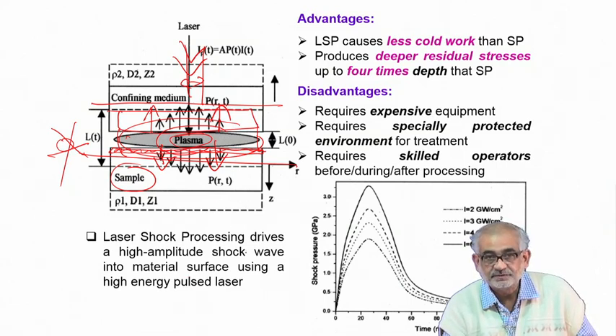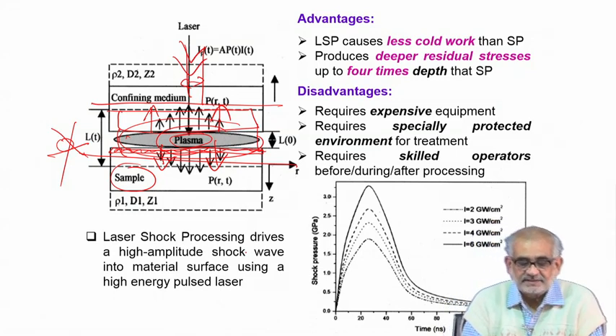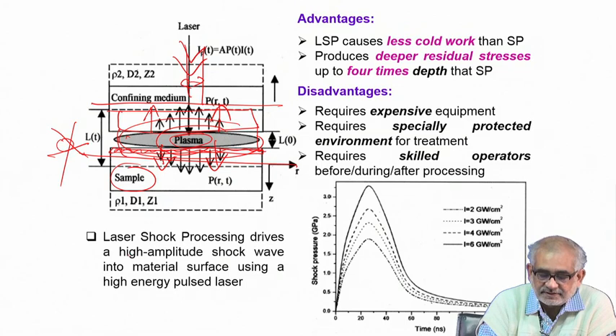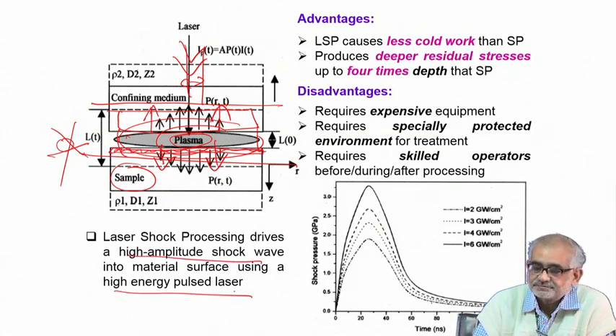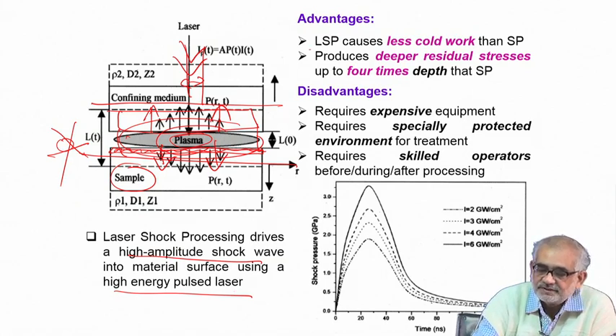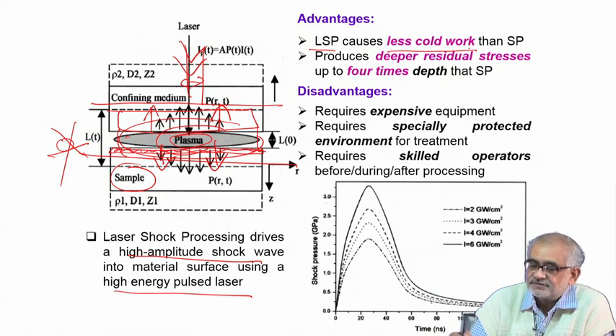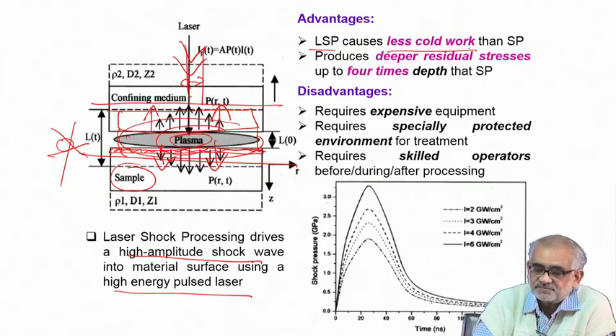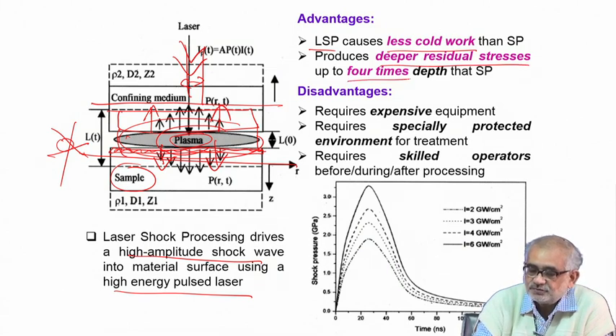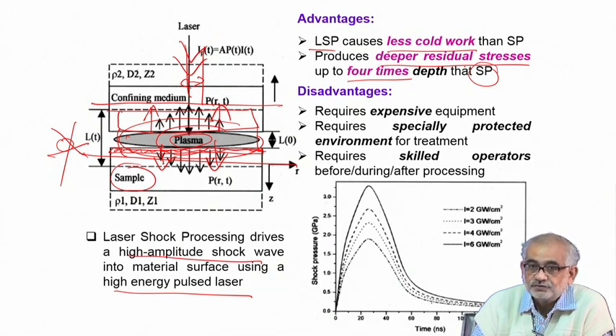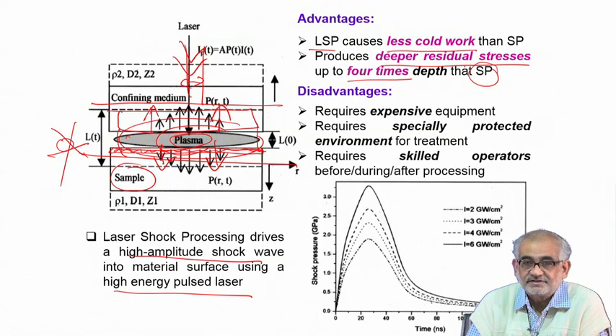The effect is felt over a wider surface area, and the amplitude of the shock wave generated is much more intense because of the high energy pulsed laser. The typical advantage of laser shock peening is that the depth of cold work generated is less, but because the intensity of the plasma is higher, you actually produce a deeper residual stress — which could be 4 times the depth of residual stress achievable through shock peening. Laser shock peening is therefore more effective than shock peening and certainly more effective than shot peening.